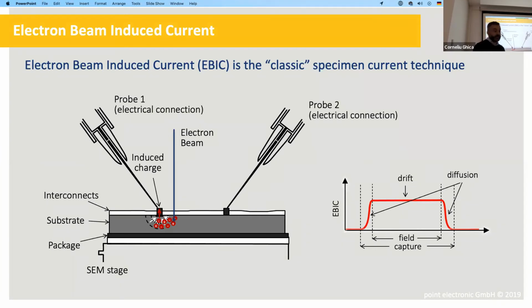It also happens with ceramics, which also have a band gap. So it always happens. Sometimes the electron hole pairs recombine to produce light, so there will be cathodoluminescence. Sometimes they recombine to produce X-rays, or they recombine to produce just heat. But most of the time, the information is not collected because they recombine very quickly. They attract and they recombine. However, if there is a local electric field, and this is the second important requirement for the technique to work, if there is an internal electric field in the material, in the device, then the electron hole pairs are separated, and they follow the electric field. And then they no longer recombine, and we have a chance to collect them.